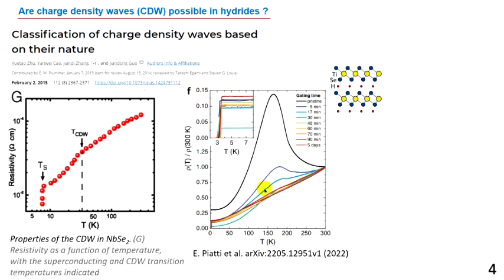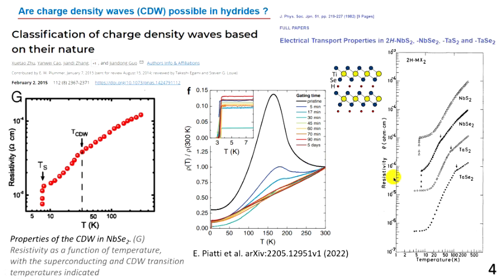We see absolutely similar wave of electrical resistance in the normal state of this compound. Okay, and the third example is a series of sulfides such as niobium disulfide, tantalum disulfide, tantalum diselenide. We also can see in all of these compounds there is a kink, or wave, in electrical resistance in normal states of these compounds. Very similar to something we saw in hydrides in previous slides I showed.